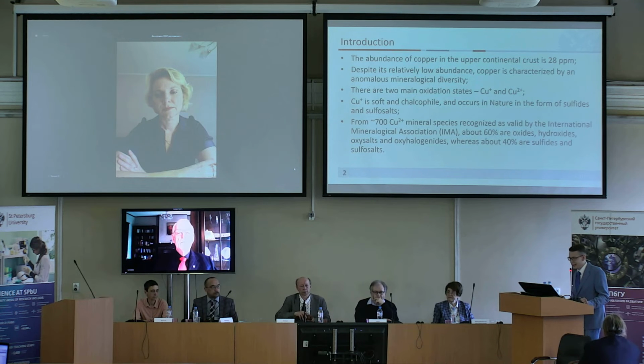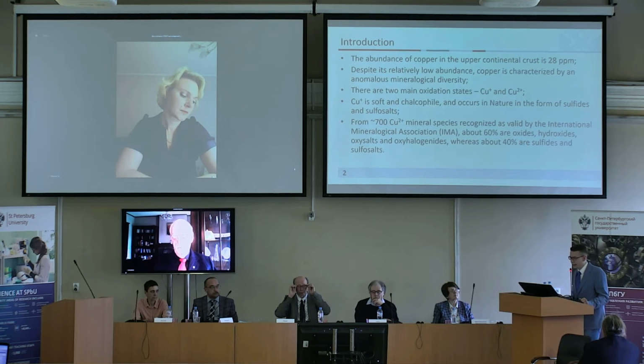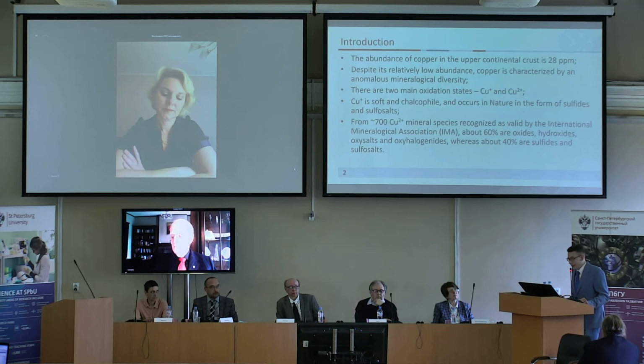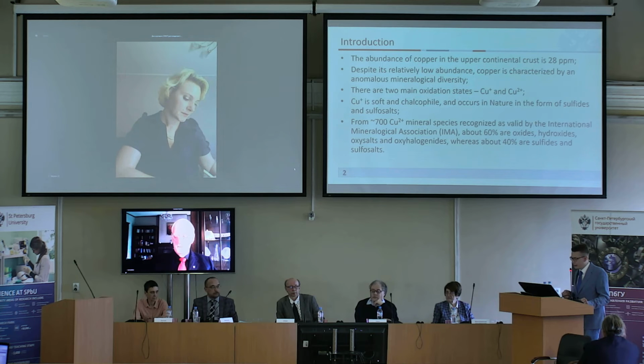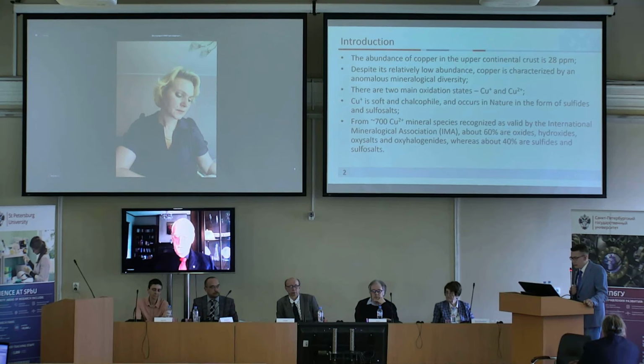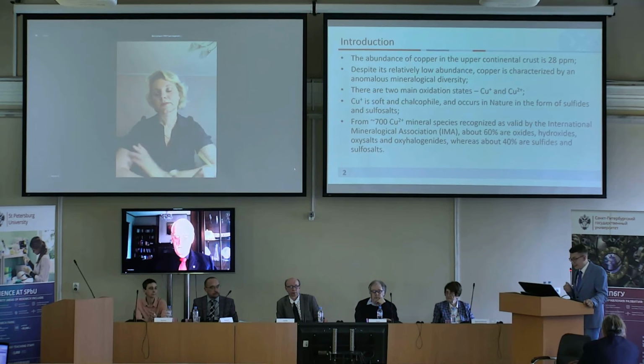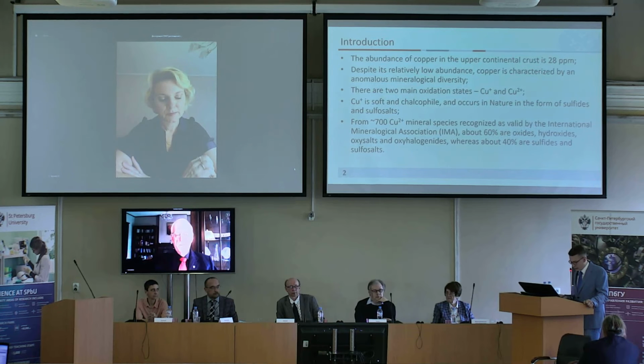The copper content in the upper continental crust is 28 ppm, and despite its relatively low content, copper is characterized by an anomalous mineralogical diversity. In nature, copper can be found in 2 degrees of oxidation, univalent and divalent. Univalent copper is soft and chalcophilic, and divalent copper is hard and lithophilic, and tends to form oxygen-containing mineral species. Indeed, of more than 700 divalent copper minerals approved by the International Mineralogical Association, over 440 minerals are oxygen-containing.